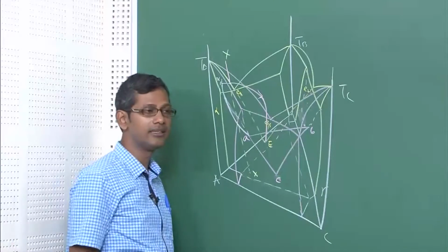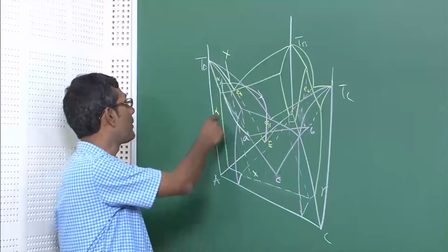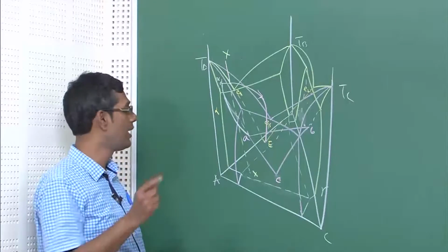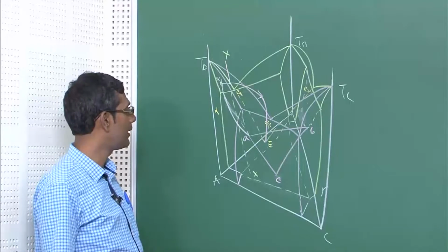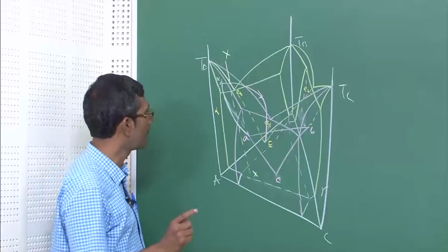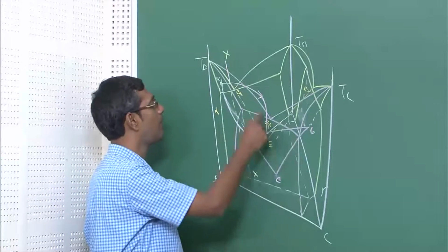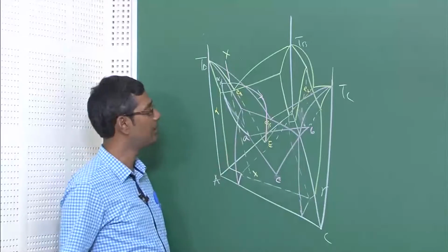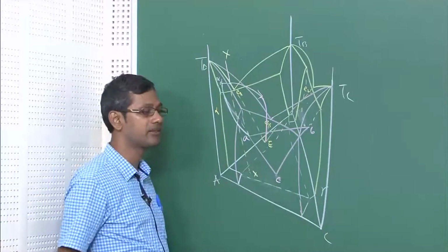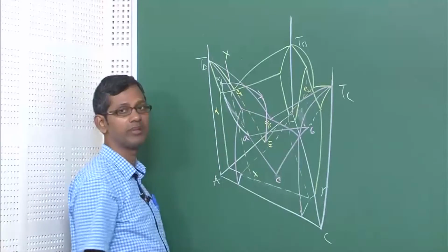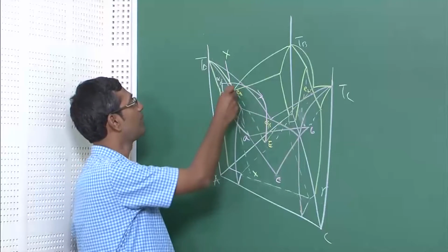Okay. And this is the reason I have basically touched upon the basic thing of the eutectic, where there is no primary phase field A, alpha, beta or gamma, only pure A, pure B, pure C exist. Okay. And whenever, another important thing I should tell you, that whenever this precipitates both alpha and gamma, there will be 3 phase equilibrium between alpha, gamma and the liquid, and that will look like a triangle inside these. I am not drawing it, this will make the picture very complicated and you will not be able to appreciate that. So, it is not difficult for you to understand.